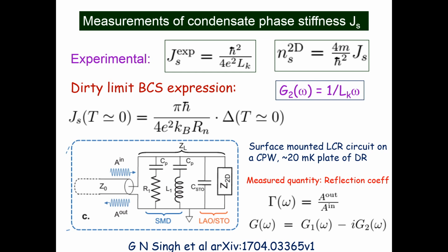And so I can write down my phase stiffness. The experimental value of phase stiffness is basically these constants times 1 over the kinetic inductance, which I am measuring from here. And then I can rewrite this expression, and that gives me the number density of the superconducting pairs in terms of the phase stiffness. So I can deduce this quantity once I know this. I can also write the phase stiffness using the BCS expression in the limit of 0 temperature. The BCS theory gives us the phase stiffness equal to this, 1 over normal state resistance and the gap parameter at T equal to 0.